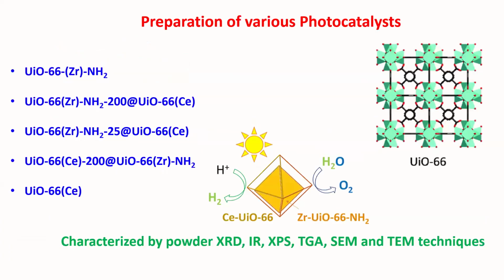So for the first example, we have selected these catalysts. We have UiO-66 zirconium amino. These amino groups are functionalized on the 1,4-benzene dicarboxylic acid linker, and here you have zirconium 4+ as the metal center. And in this case, UiO-66 cerium: instead of zirconium, you have cerium metal. So this is zirconium 4+, this is cerium 4+. We have prepared a series of samples. This is pure UiO-66 zirconium amino, and this is UiO-66 cerium.